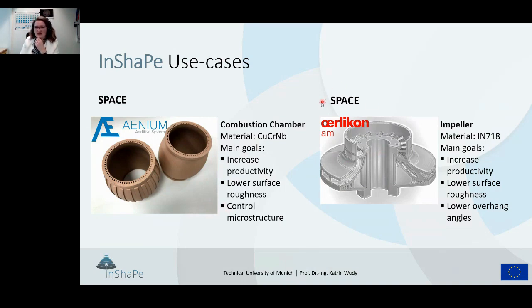Another use case in the area of space or aviation is from Oerlikon AM, which is an impeller structure. The material here is an Inconel material, and the aim is mainly to increase the productivity of the process, to lower again the surface roughness on specific surfaces, to avoid support structures completely, and that's why to also lower the overhang buildability. And here you see a cross-section of this component.